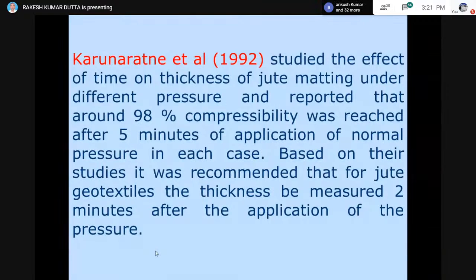In this study, he did compressibility and thickness related studies of the polymeric materials, and some natural materials were also used. What he concluded from this study was that the jute matting under different pressure shows around 98% compressibility, and this 98% compressibility is reached in 5 minutes upon the application of the normal load.